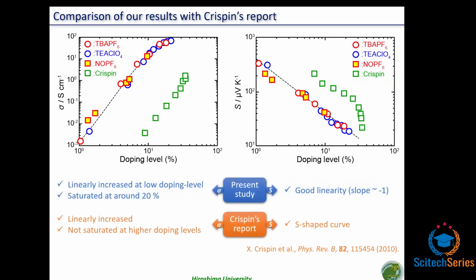Professor Crispin also reported the dependencies of thermoelectric properties of P3HT chemically oxidized by NOPF6. However, these tendencies are completely different. In our case, the electrical conductivity linearly increased at low doping level region and was saturated at around 20%, and the Seebeck coefficient showed a good linearity. On the other hand, in the Crispin's report, electrical conductivity just increased linearly and was not saturated even at higher doping levels. And the dependencies of Seebeck coefficient showed an S-shaped curve. Why are these differences observed?